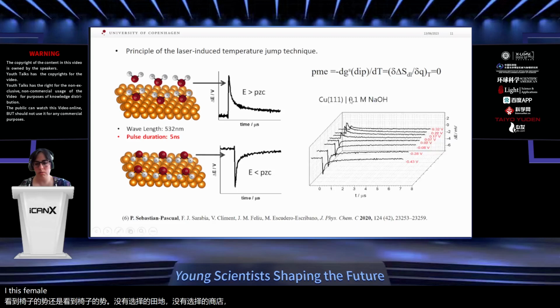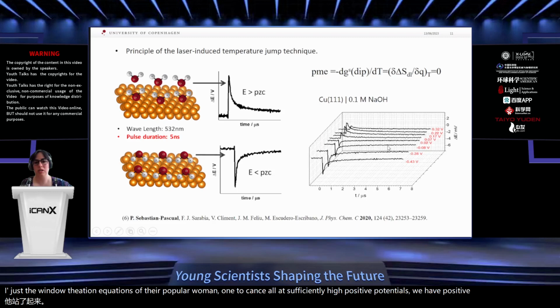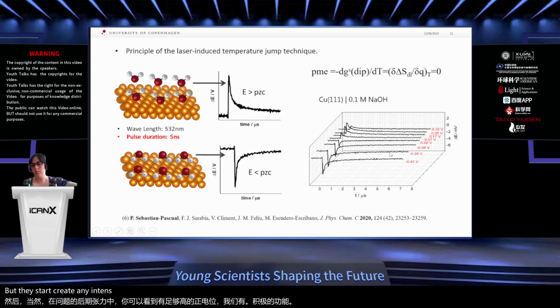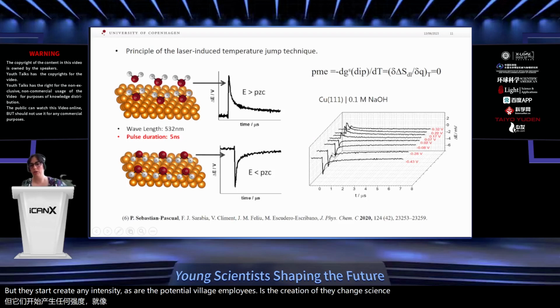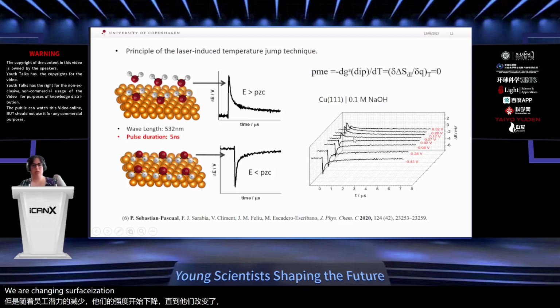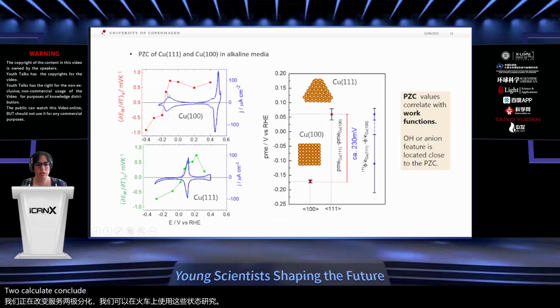And here is how this experiment typically looks. I'm just showing the laser transients of copper 111. As you can see, at sufficiently high positive potentials, we have positive transients, but they start to decrease in intensity as the potential of the electrode decreases until they change sign, because we are changing the surface polarization. And we can use this data, these transients, to calculate the thermal coefficients.